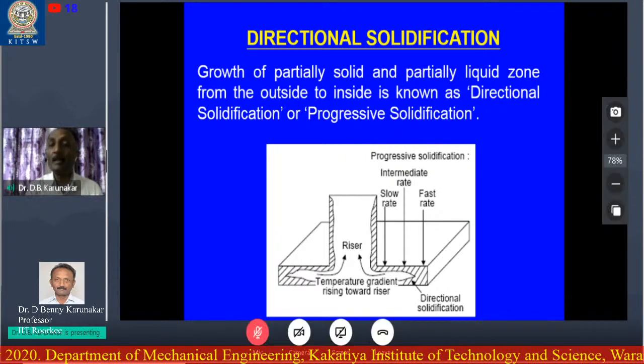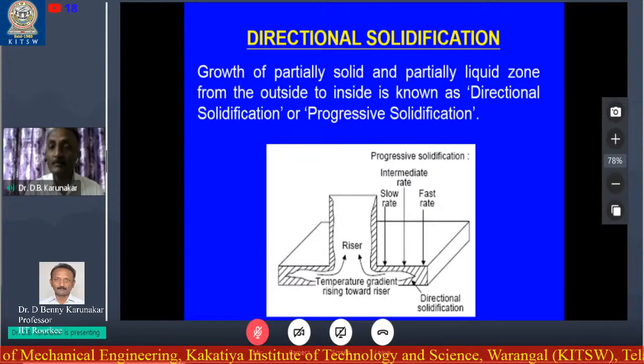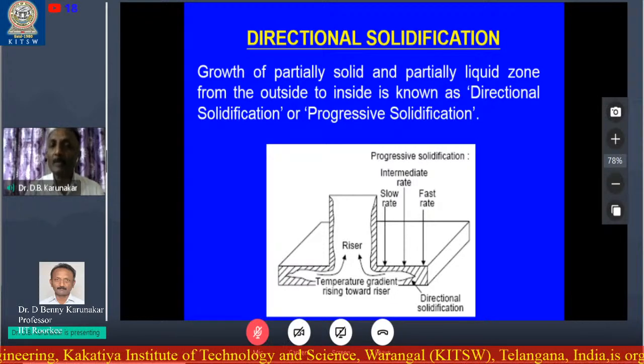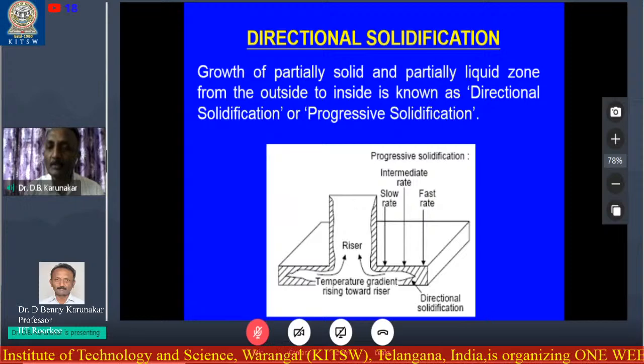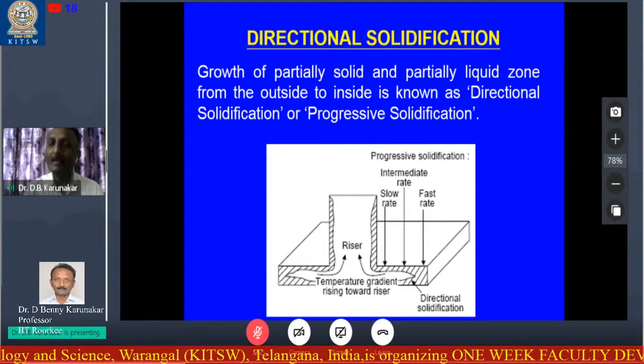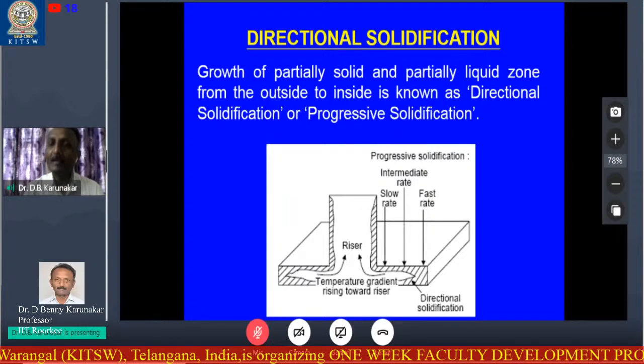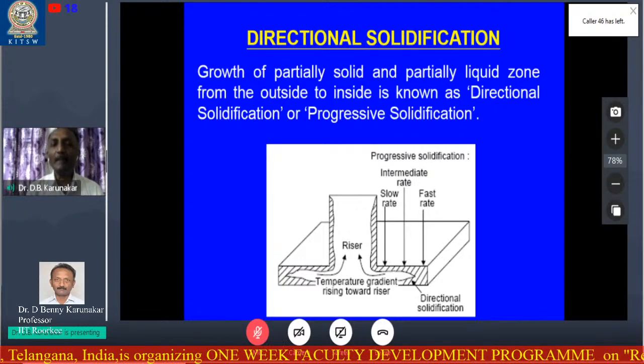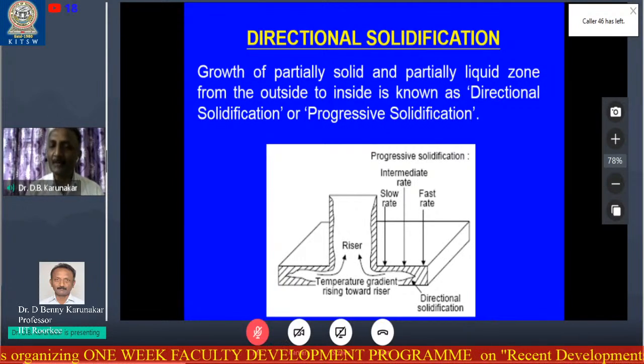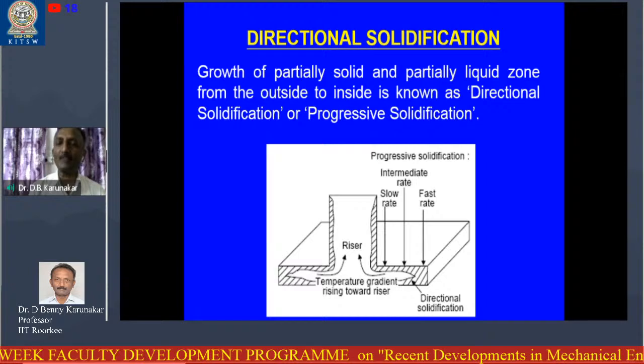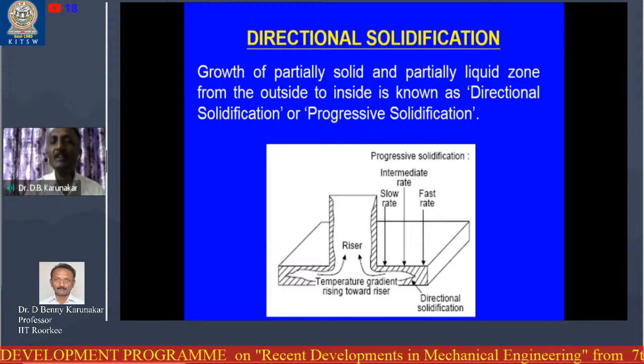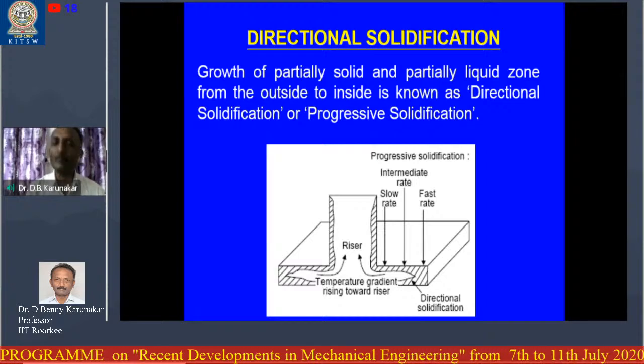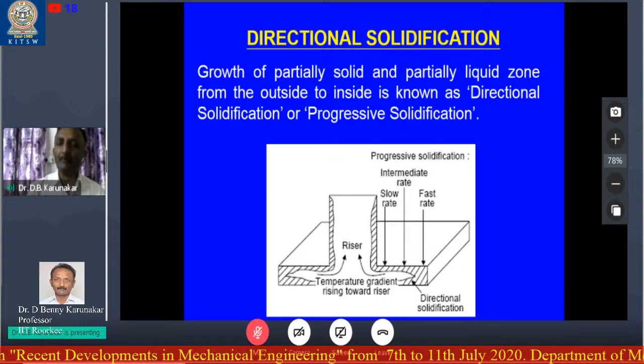Now you tell me which solidification is good? Is it the progressive solidification or the directional solidification? Certainly, directional solidification is better, but we can't make the progressive solidification zero. Progressive solidification will always be there. The only thing is, you ensure that the progressive solidification is smaller and the directional solidification is larger.